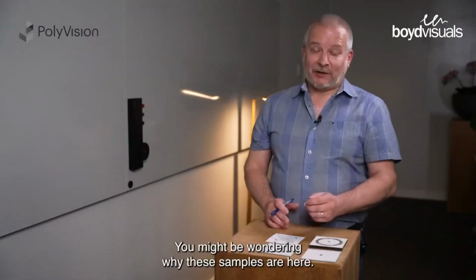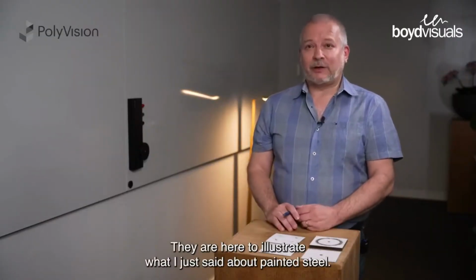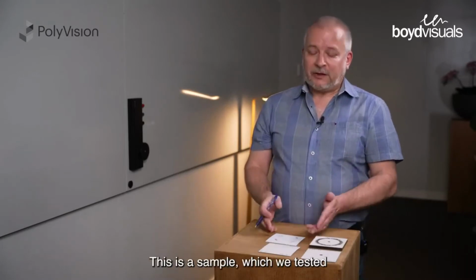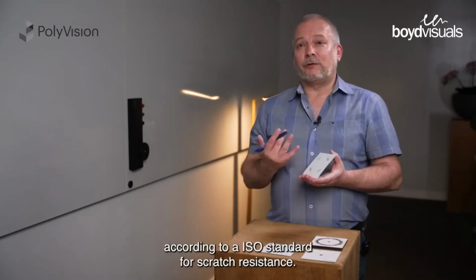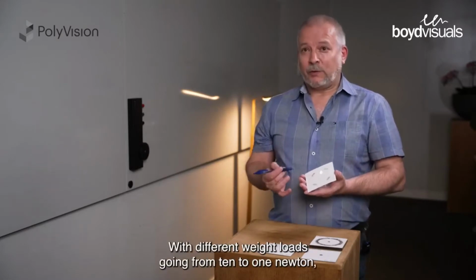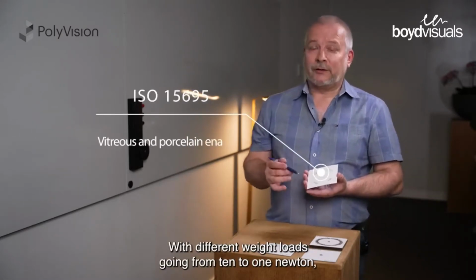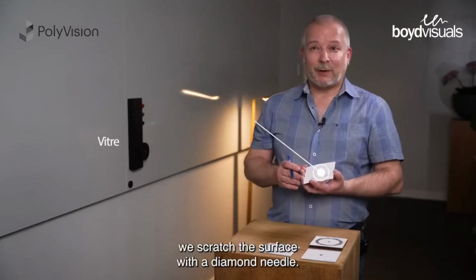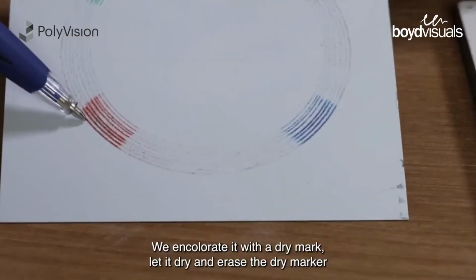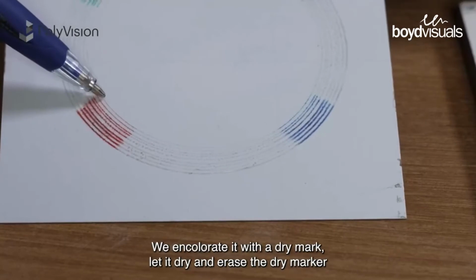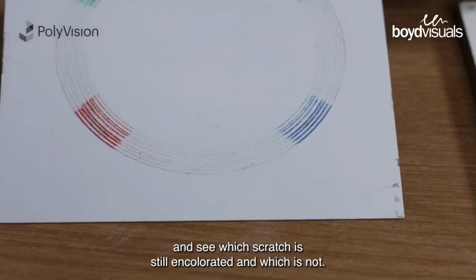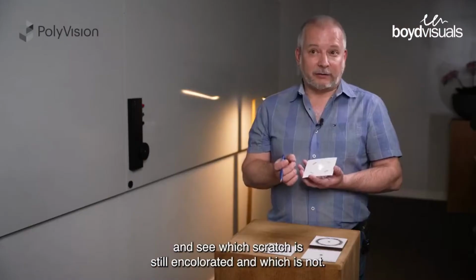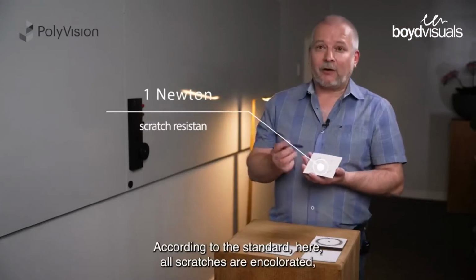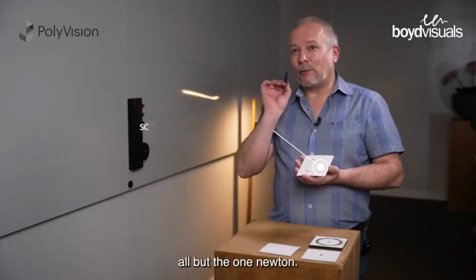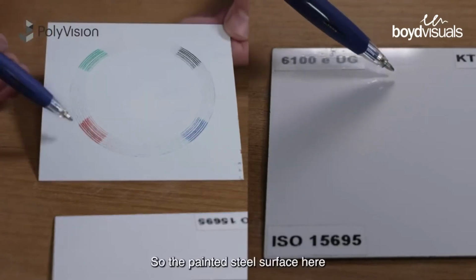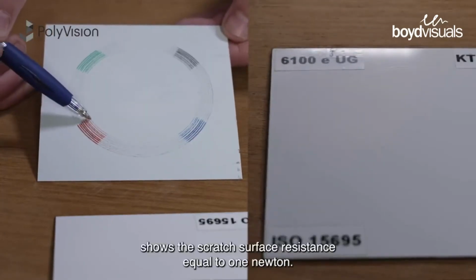You might be wondering why these samples are here. Well, they are here to illustrate what I just said about painted steel. This is a sample which we tested according to an ISO standard for scratch resistance. With different weight loads going from 10 to 1 Newton, we scratch the surface with a diamond needle. We incolorate it with a dry marker, let it dry, and then erase the dry marker and see which scratch is still incolorated and which is not. And according to the standard, here all scratches are incolorated, all but the 1 Newton. So the painted steel surface here shows a scratch resistance equal to 1 Newton.